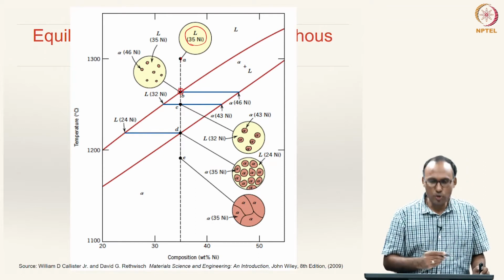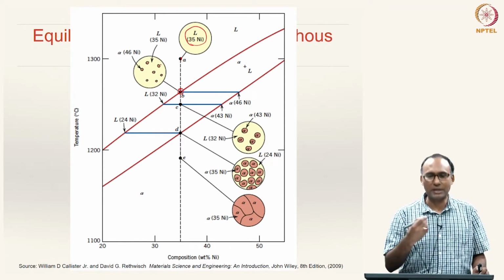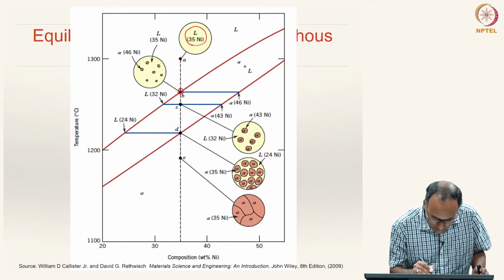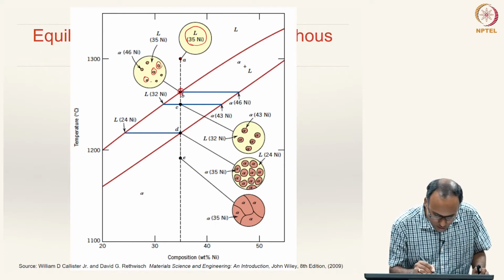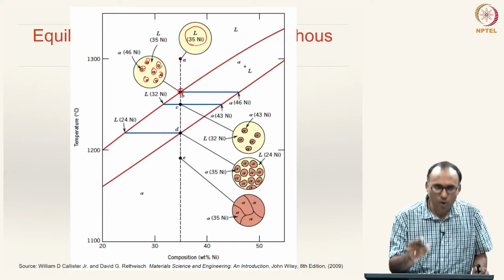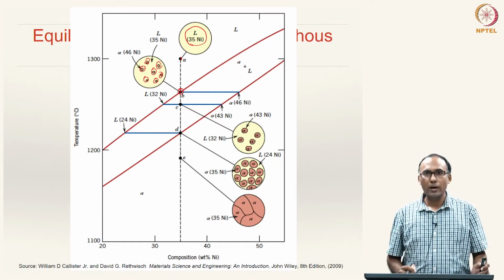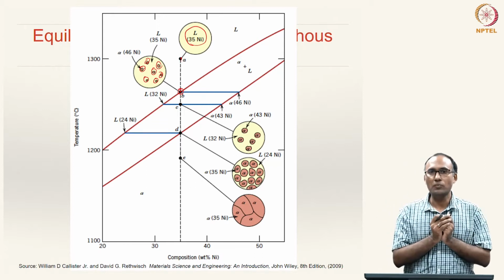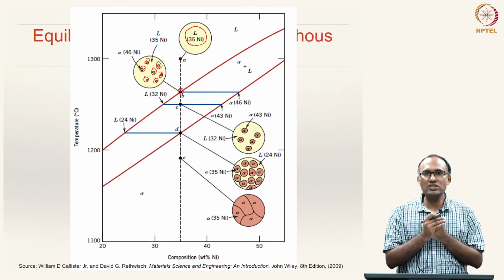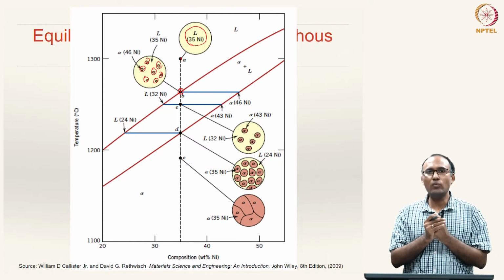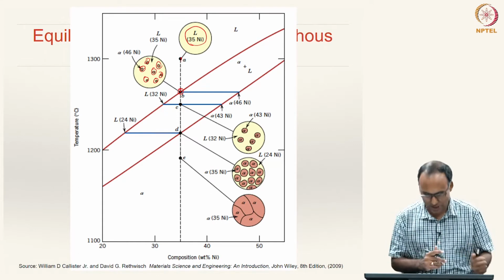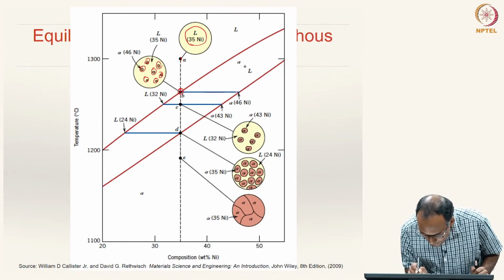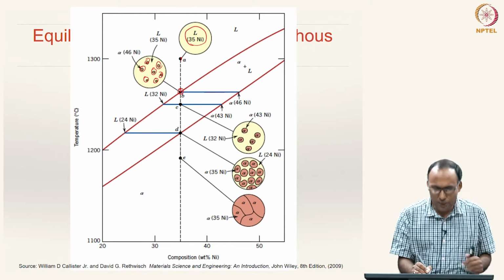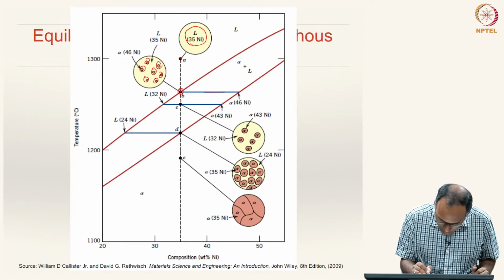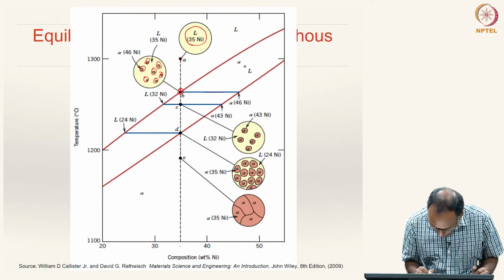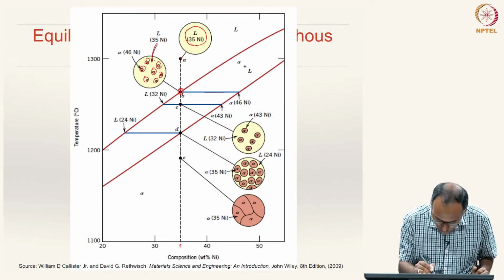small nuclei of solid solution start forming. So, you can see these are all small nuclei of solid forming, but you are already in the two phase region now. Now, since you are in the two phase region, you should draw a tie line and say what are the compositions of the liquid and solid phase. So, now you draw the tie line,